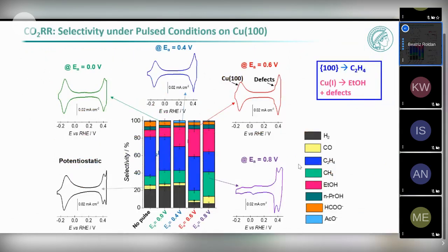But the pulses are not only doing that. So I'm going to show you here the selectivity for different pulse treatments. I'm going to ask you to look at this 0.6 volts. This is when we were having copper plus species. And I'm going to ask you to look at these two colors. In blue, this is ethylene, and in pink, this is ethanol. So if you don't apply any pulses, the copper 100 surface makes a lot of ethylene. And this remains when you apply the pulses, but when you apply the positive pulses, we first suppress the formation of hydrogen, this is here in black, and you increase the formation of ethanol very significantly.